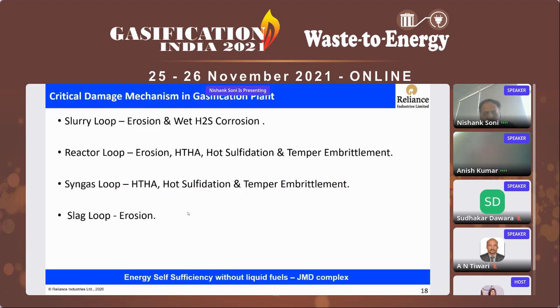The next one is the reactor loop. In this loop, the complete hot gas path is made up of alloy steel with internal refractory lining for erosion and temperature resistance. Any damage like erosion, HTHA, sulfidation will occur only if the internal reactor lining and protective internal coating get damaged. Moving to the next loop, the syngas loop.